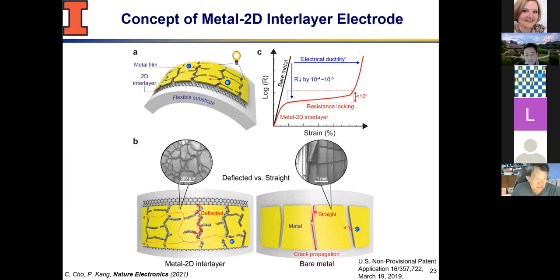So this is what you see if you have, let's say, PDMS with gold, copper, metal, or the same metal with graphene underneath and you bend it. Similar to what the previous example showed, you see very straight cracks in the bare metal or metal on PDMS. When you have a single layer graphene, you start to see something that's drastically different. So it's no longer straight. So that's what you can see. The length scale of fractures are also quite different. I'll talk a little bit about that.